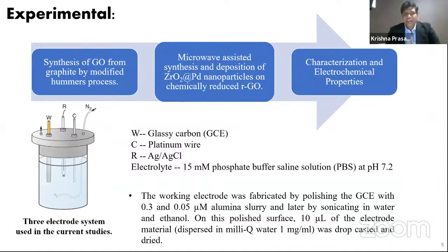And these studies have been carried out in a 3-electrode system, wherein the working electrode is a glassy carbon electrode, the counter electrode is a platinum wire, and the reference electrode is a silver-silver chloride electrode. And the electrolyte used was a 15 millimolar phosphate buffer saline solution at a pH of 7.2. And the working electrode was fabricated by polishing the GCE and later drop casting 10 microliters of the electrode material, which was dispersed in milli-Q water at 1 milligram per ml concentration. After drop casting, the electrodes were dried under vacuum at 70 degrees Celsius and were used for further studies.